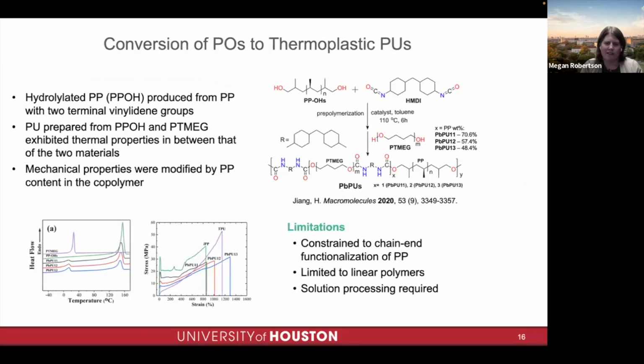We were inspired by this article by Jiang, which was published in 2020, and this actually got us started down this line of research. What they did was they made end-functionalized polypropylene, where there are exactly two hydroxyl groups per chain. The hydroxyl groups can only be at the ends. And then they react it with a traditional diisocyanate curing agent to form a polyurethane. So now they have a linear polyurethane. So this is the thermoplastic class that I mentioned on the previous slide, not the thermoset. And they actually had a co-monomer so they could bring in some softer segments and tune the properties in that way. So this was a very nice proof of concept that we can make a polyurethane from an olefin like polypropylene.